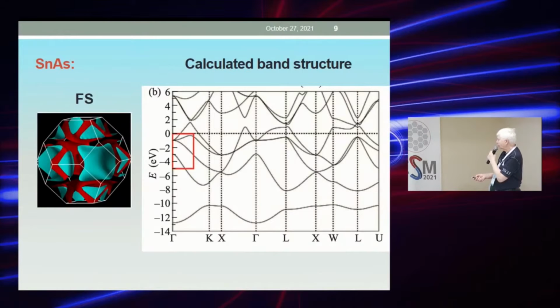So here is the Fermi surface corresponding to the zero energy of this calculated band structure. And we studied in experiment this tiny range of energies, because we did measurements with the laboratory photon source of a helium lamp. It's important to say that the calculated band structure is slightly sensitive to the spin orbit coupling for different orbitals, but is very sensitive to the bulk or slab shape of the investigated samples.